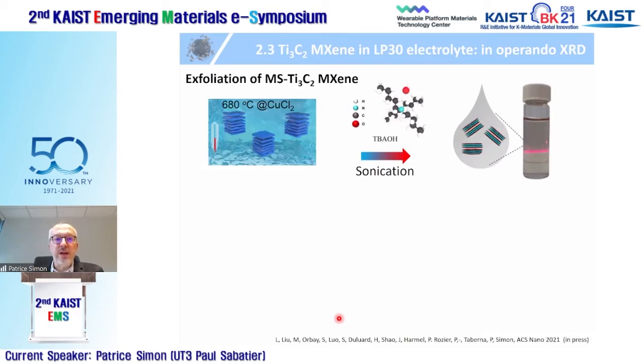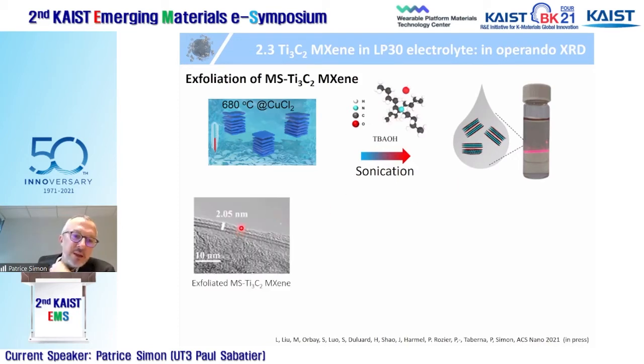Then, what we tried to do was to improve the electrochemical performance of our material by doing an exfoliation of this molten salt Ti3C2 MXene. So the exfoliation of molten salt prepared MXenes is more complex than the etched in aqueous electrolyte. But what we did was we took our MXene, we mixed with TBAOH, a big cation, strong base. We did sonication and we did a centrifugation to recover the supernatant. And what you observe is that, yes, you have a kind of delamination, exfoliation.